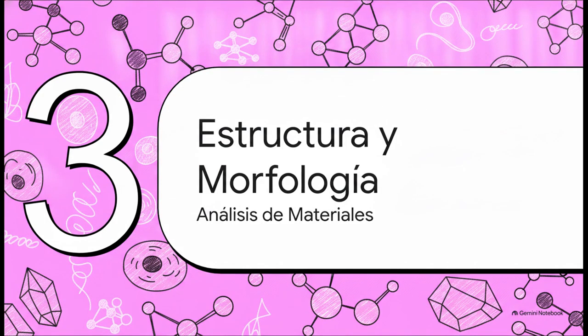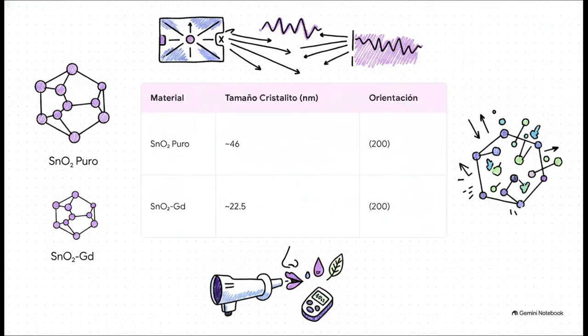That brings us to Section 3, Structural and Morphological Results. All right, so what did the XRD and infrared analysis actually tell us? Well, they confirmed a single phase of tin dioxide with a tetragonal rutile-type structure. No secondary phases popped up at all, which is great because it proves the gadolinium was perfectly incorporated into the matrix. We also saw a very clear preferential orientation along the 200 plane across all films.